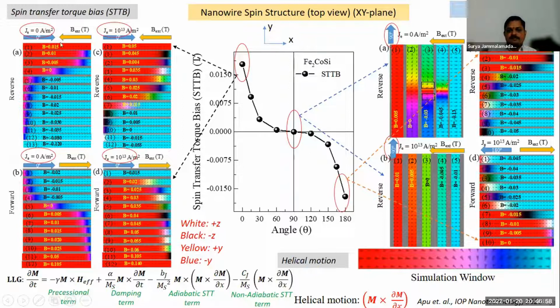Okay, so now if you look at the left hand side panel, we have JE equal to zero. That means the current density, the spin transfer torque, is zero over here, and only the magnetic field is swept. And over here also, JE is zero. The spin transfer torque is zero. Only the magnetic field is swept. And we do see a smooth variation for the domain wall within the wire. Okay. As soon as we switched on the spin transfer torque bias, we don't see a smooth variation for the domain wall within the nanowire.